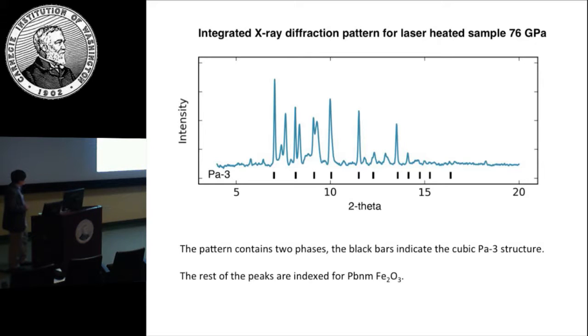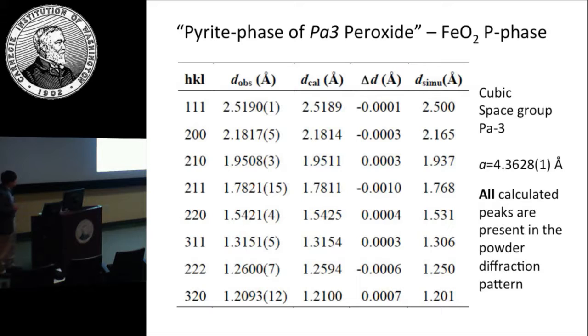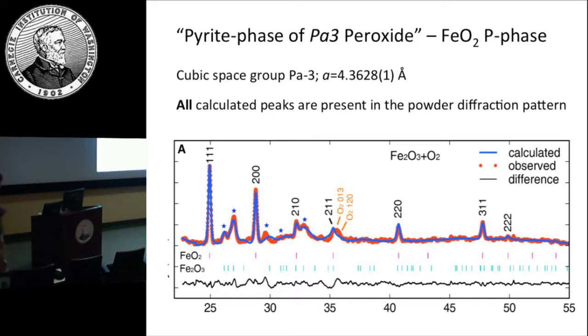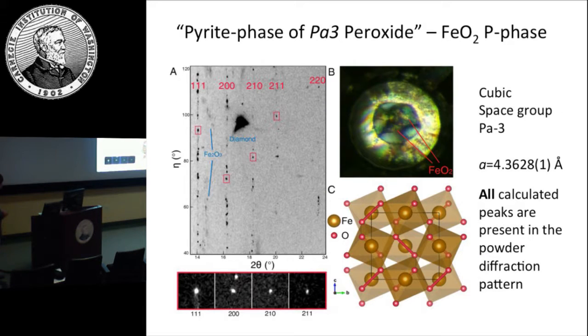So this is Pa-3, and you can see that aside from the Fe2O3, some unreacted part, all the strong peaks are Pa-3. That's cubic, so it's very simple to compare with. If you compare with this, you have the calculated d-spacing and the measured d-spacing, and they agree very, very well. It has all the calculated peaks, and all the peaks are accountable. We refined this and found a very small difference, with some residual Fe2O3 left there. The structure is the pyrite structure, or Pa-3 structure.